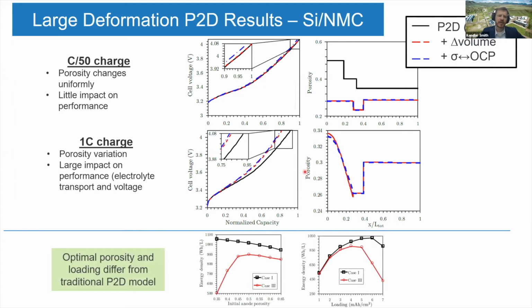And so just to point out a difference from a traditional P2D model, which are the black lines here, versus this new large deformation model, as you increase the initial anode porosity of your design, a P2D model predicts that you want that anode porosity to be as small as possible. Our model predicts that there's some sort of optimal there around 45 to 50%. And similarly, as you increase in loading, the optimal loading for these cells is a little bit different. I believe this is probably at a 1C rate between what a P2D model would predict as well as the silicon model.